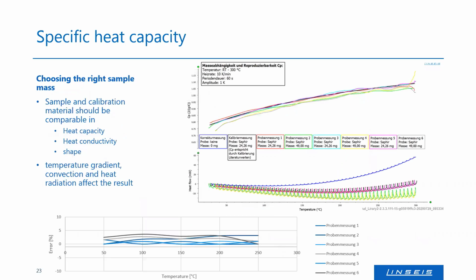Another investigation was the choice of the right sample mass, because this also affects our result here. So I've checked, okay, let's choose something between 25 and 50 milligrams. And what we can see here is that the deviation is around 3% error. But it is important: the heat capacity of your sample, the heat conductivity, and really important, the shape of your sample, will affect the accuracy of your result here. Because the heat has to go through the crucible into the sample, the shape is pretty important here.